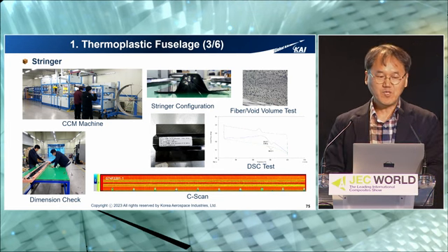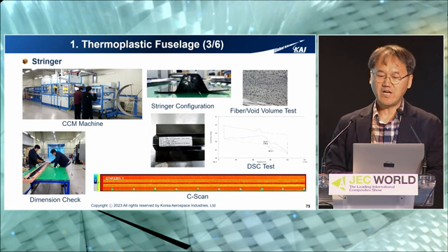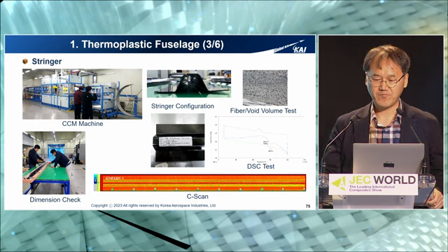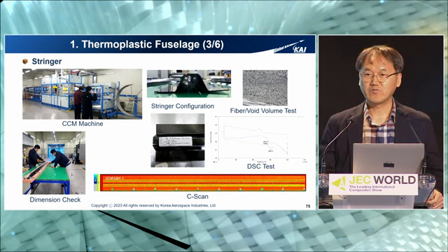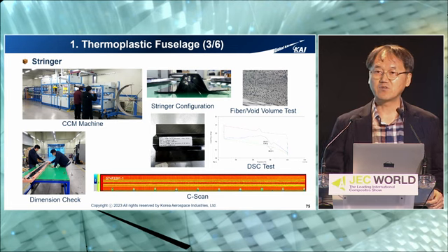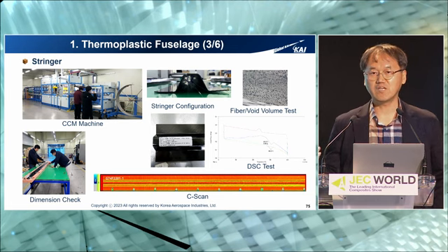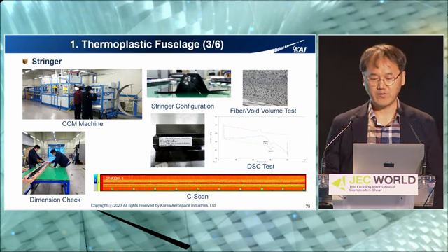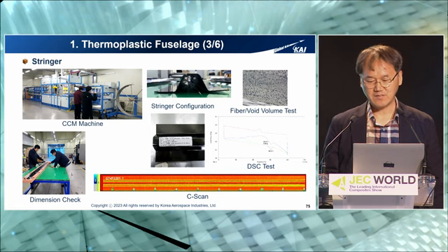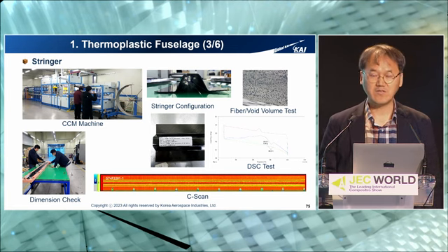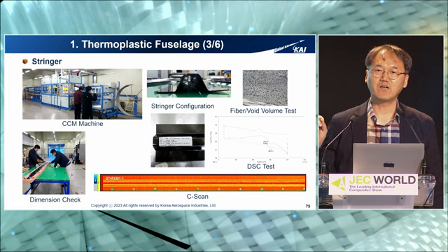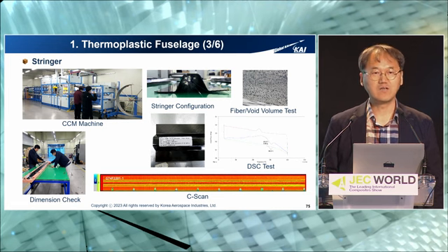This is a CCM machine to make a stringer, having a hat section stringer. We conducted fiber volume and void volume tests, and we accept the minimum percentage of void volume, and dimension tests and DSC tests were also conducted, and C-scan also. We spent a lot of time to check the optimum temperature, time and pressure, and we finally got the optimal process window currently.